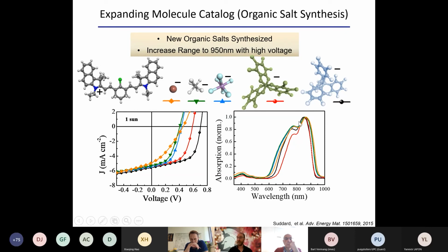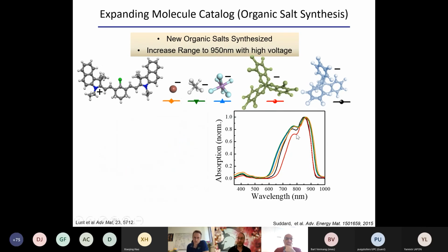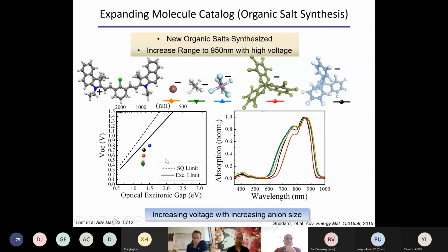But our voltage just kept increasing without changing the band gap. These are all essentially around the same band gap. They have essentially all the same absorptive properties. And so what was going on was really stunning, but we took a material with a really modest voltage for its band gap and increased it to close to its theoretical limit for an excitonic solar cell. And just for reference, this blue point was that first demonstration.